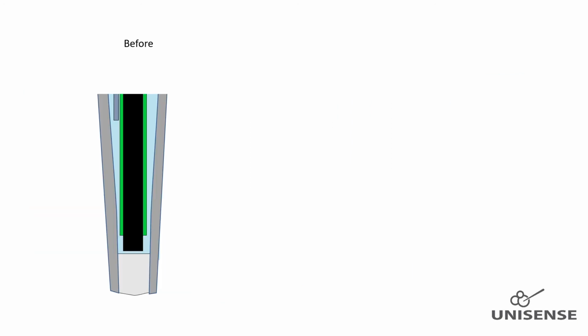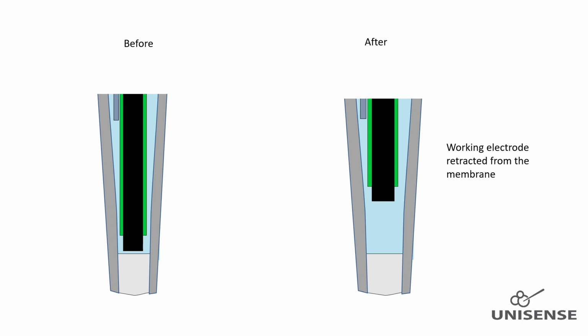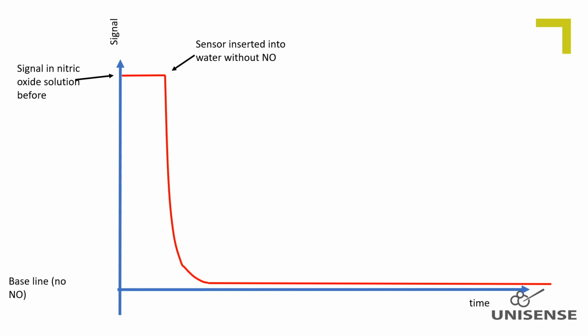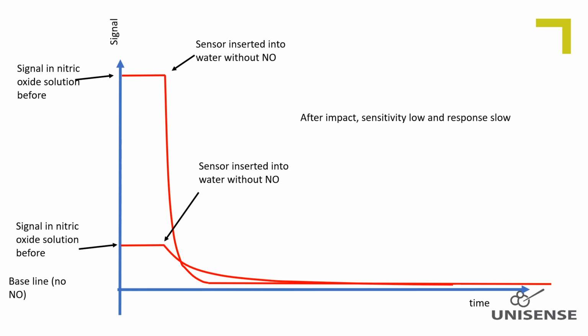If a sensor experiences a physical impact like a drop on a table, the working electrode could be displaced. If the displacement results in a working electrode retraction from the silicon membrane, the signal will be slow and sensitivity low. The sensor will still be nitric oxide sensitive, but has lost its original behavior, illustrated here by a before and after incident. It is unfortunately not possible to restore original performance.